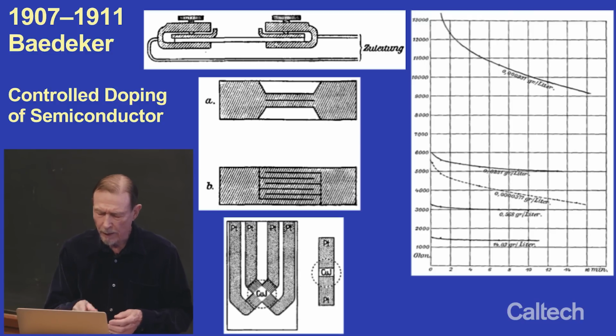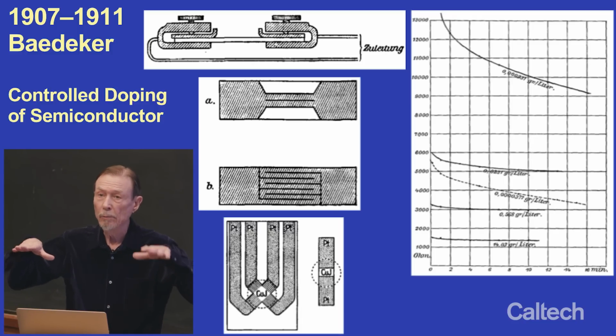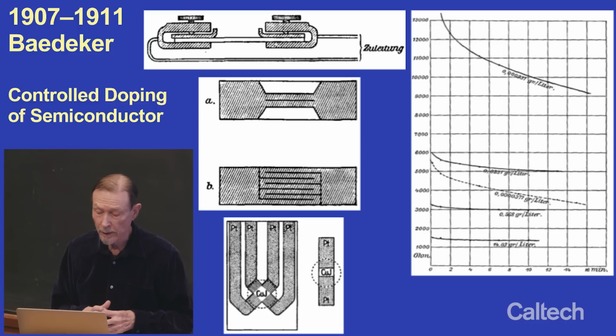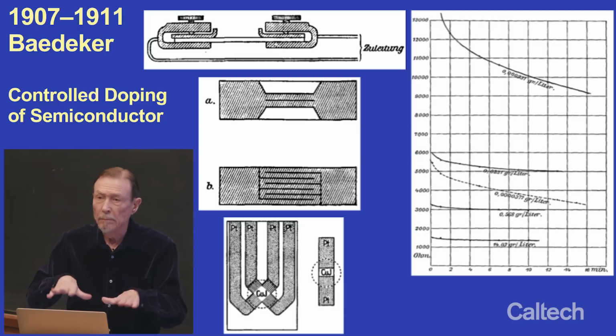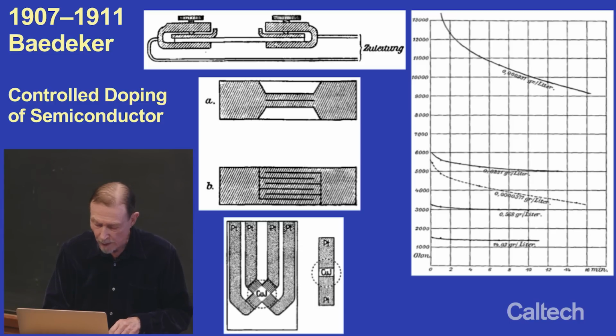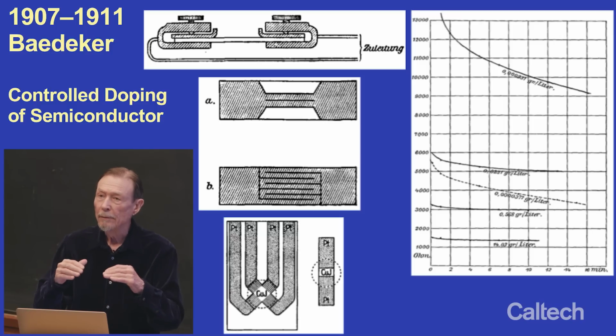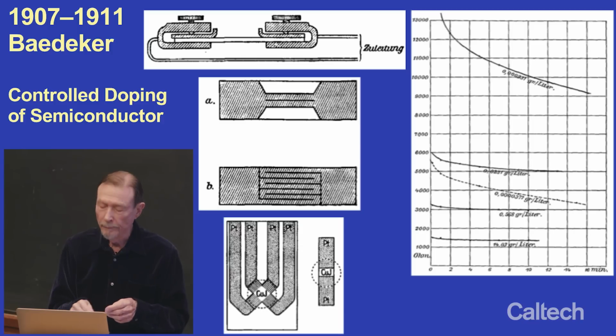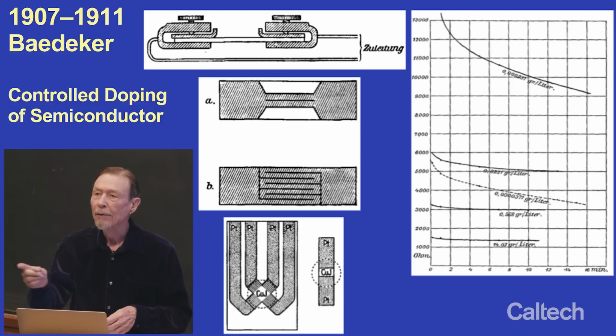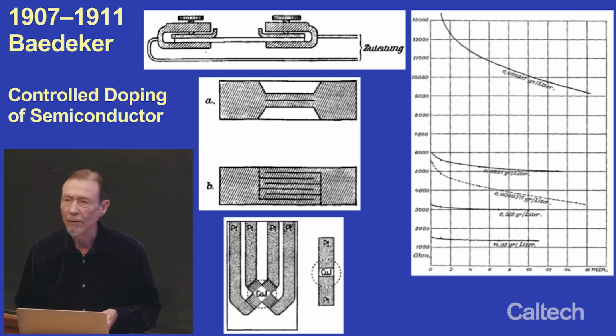The way he made them is he'd make samples like the shapes shown here, and the two big pads on the ends were where he put down the clamps that's shown in the side view on the top. And wow, I can make great big contacts, and then I can make narrow samples by, for example, in the B figure there, you see it's a serpentine. He could scribe openings in the lines where the semiconductor had been scratched away. And so you had a path that was semiconductor that was a wandering path. So it was longer, so it was easier to measure the resistance.